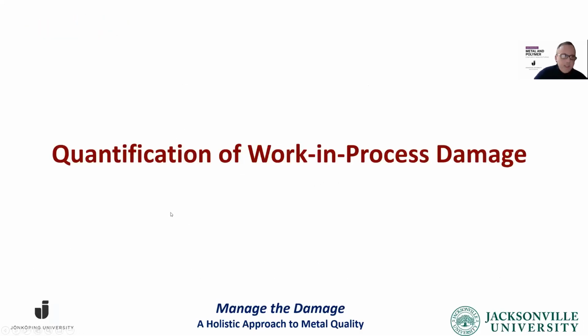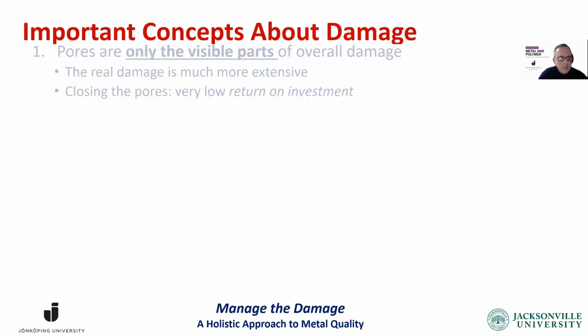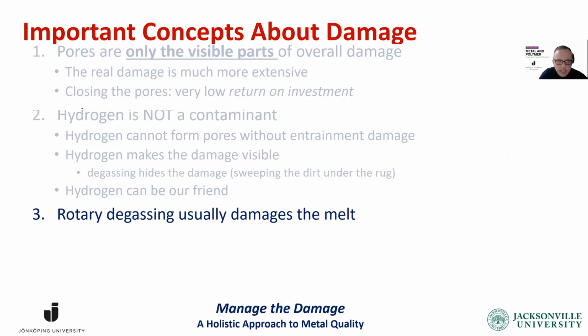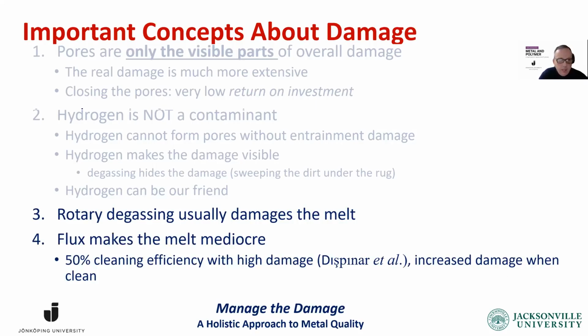Then how much damage do we have in the work in process? Important concept, again, rotary degassing actually damages the melt. Flux makes the melt mediocre. We learned from Dışpınar and his co-workers that fluxes are about 50% efficient. When you have a bad melt, it makes it mediocre. When you have a good melt, it damages it to mediocre level.